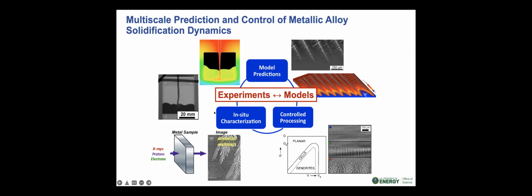And this just schematically shows the workflow that we're interested in. So we really start with in-situ characterization, where we can have a metal sample, and this can vary in thickness from anywhere from, say, 100 nanometers or 100 microns, all the way up to millimeters in thickness. We then use different novel tools and unique probes like X-rays or protons or electrons, and we use them to basically interrogate our metal sample and make movies of solidification dynamics.